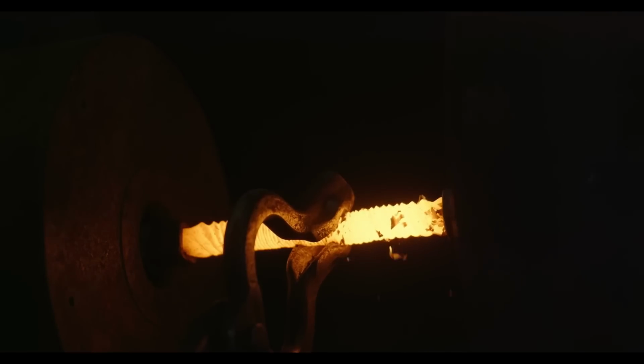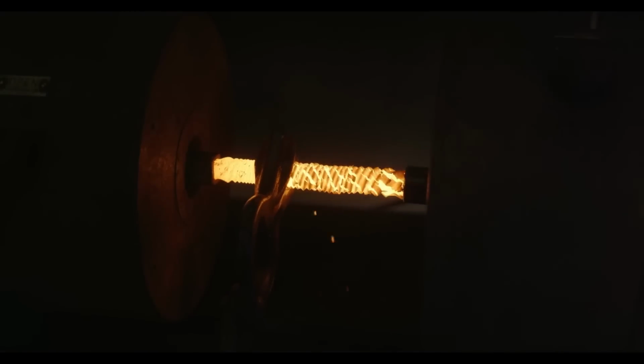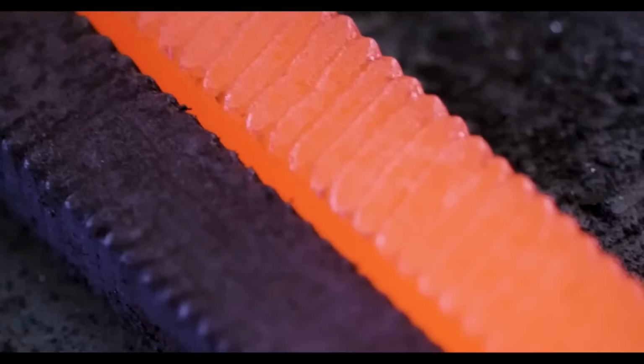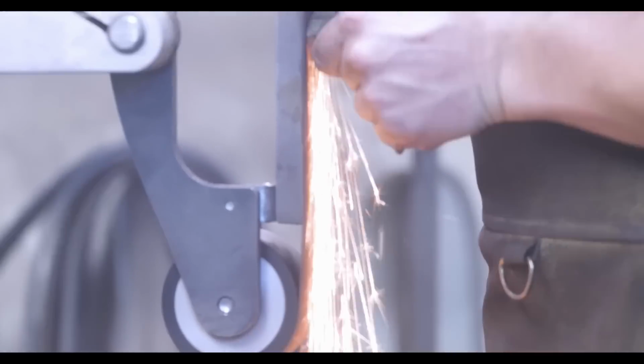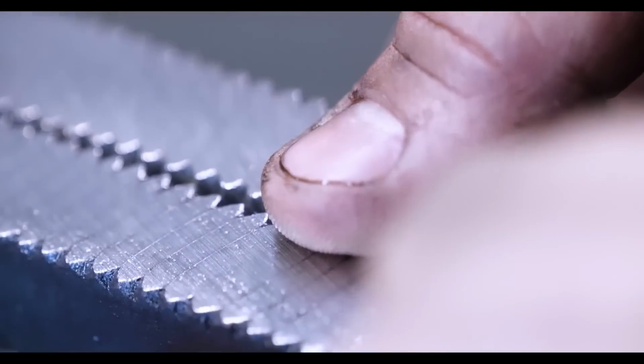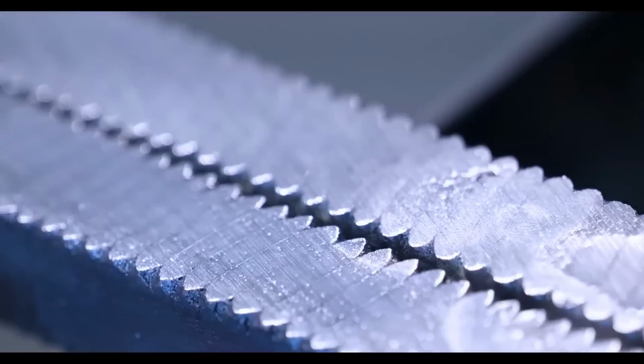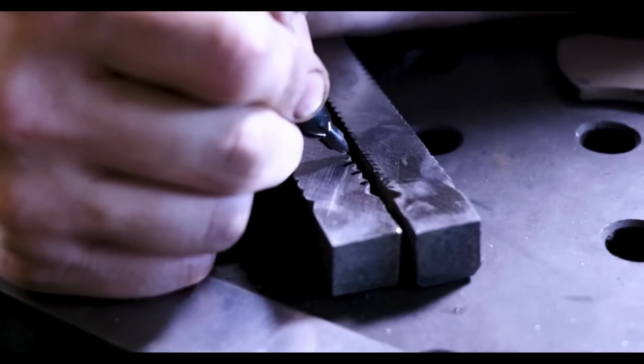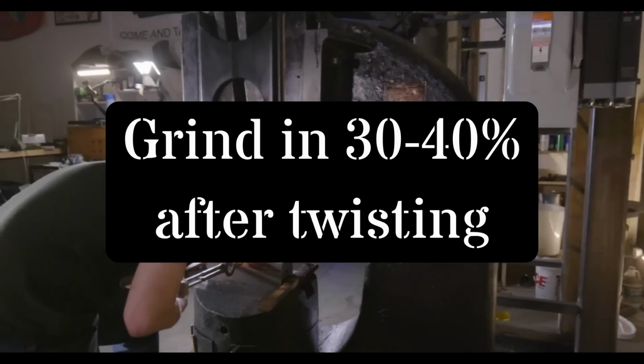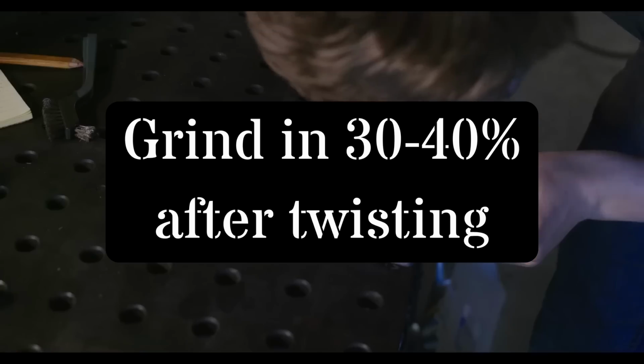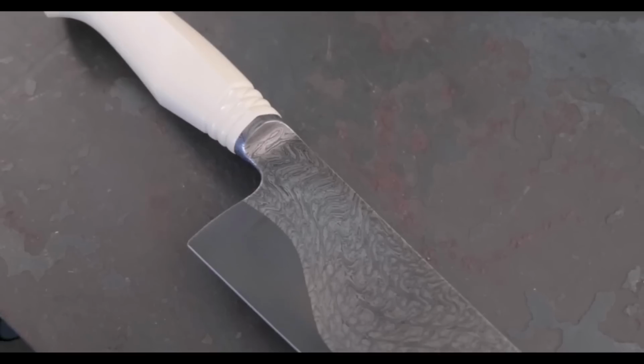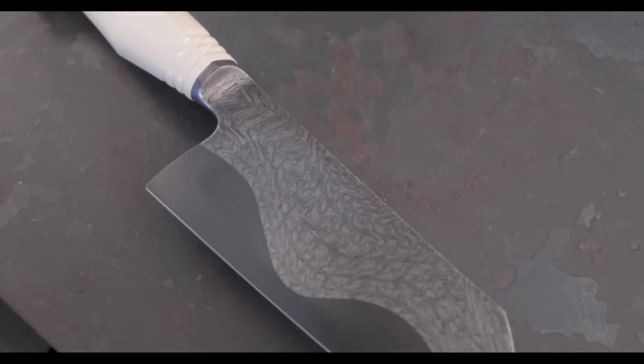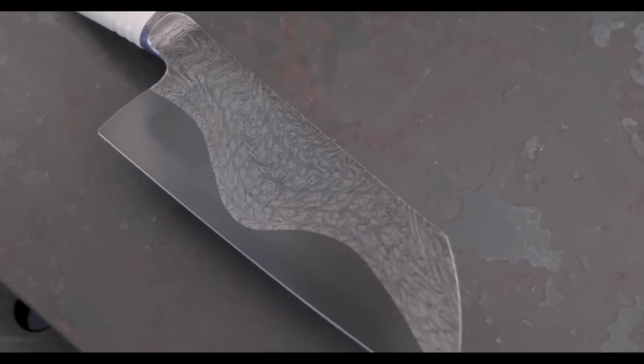The other really common method of bringing patterns to the surface is through twisting the bar. Now, the way that twisting brings the pattern to the surface is really hard to explain. Essentially, what you're left with is a dynamic pattern that as you grind farther into it, the pattern changes. And so usually you want to shoot to grind in about 30 to 40% in on the sides, and what you're left with is a really neat kind of star-bursting flowing pattern.